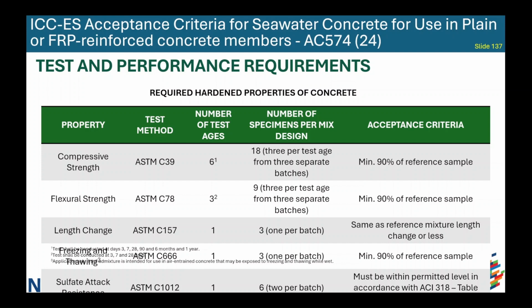For compressive strength, we are requiring testing at 3, 6, 7, 28, and 90 days, as well as 6 months and 1 year. So we want to ensure that within the first year of the seawater that there is no detriment to the compressive strength. And the acceptance criteria would be minimum of 90% of the reference sample. For flexural strength, we only are requiring 3, 7, and 28 days. But the same acceptance criteria as the compressive strength.